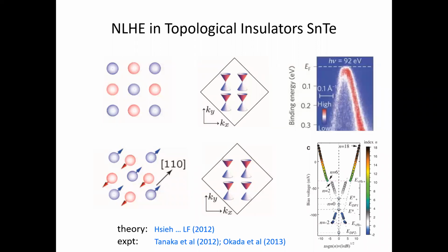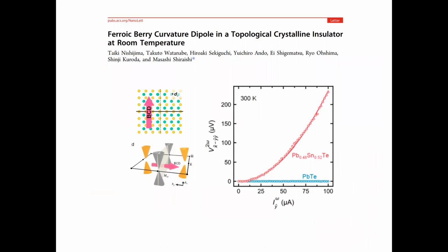And also, if you look at this Dirac energy dispersion, it is tilted, right? It has an asymmetry. So it satisfies all the ingredients I just said earlier. That's why in this 2015 paper, motivated by topological crystalline insulators, we proposed this tilted Dirac fermion model for the nonlinear Hall effect.